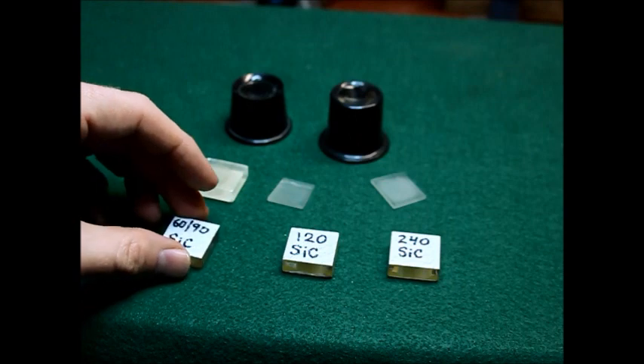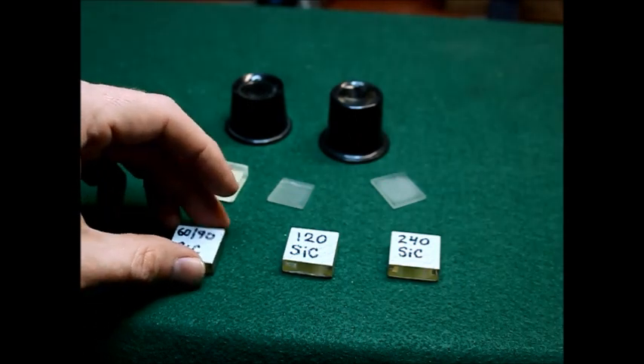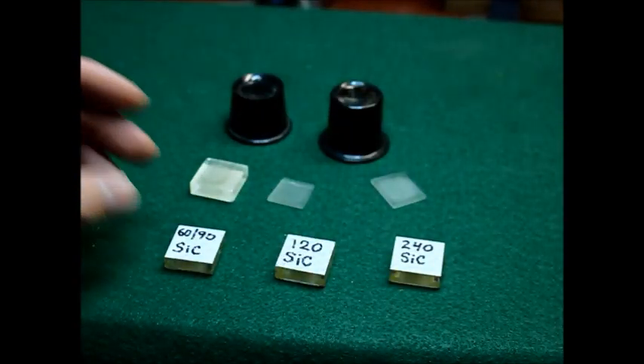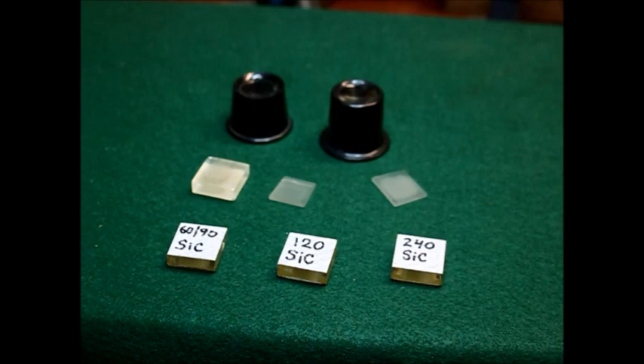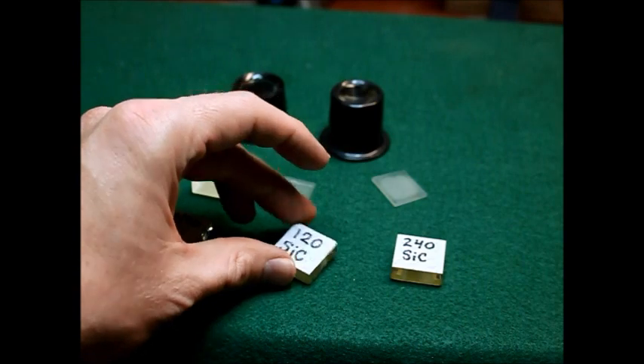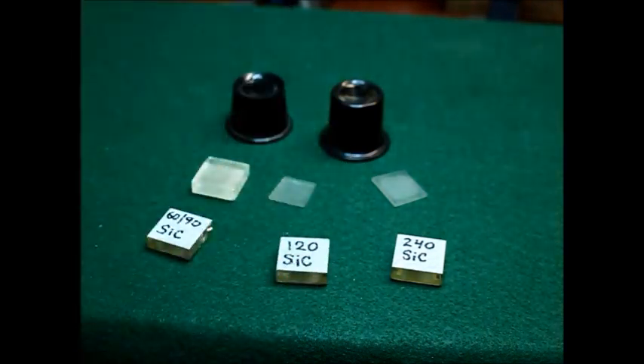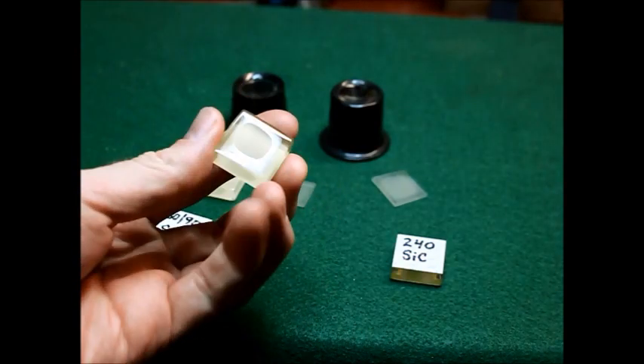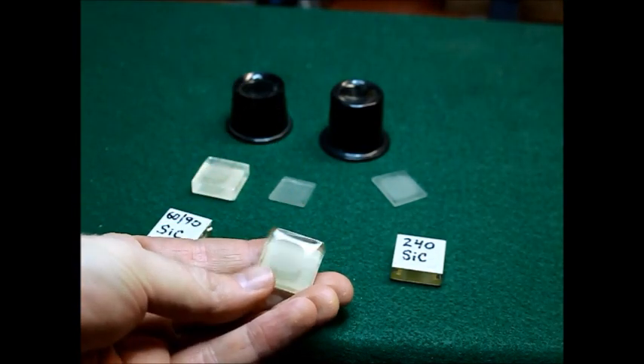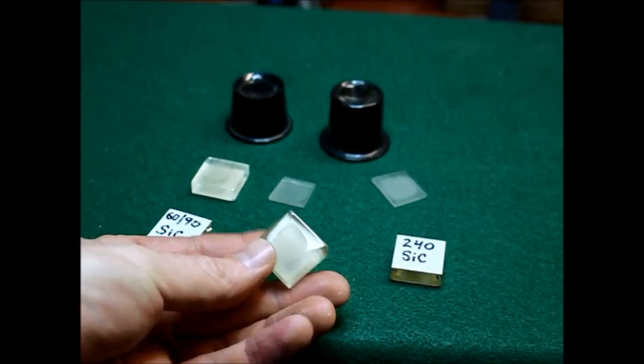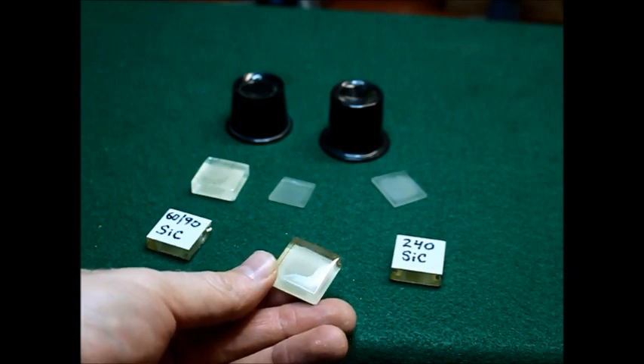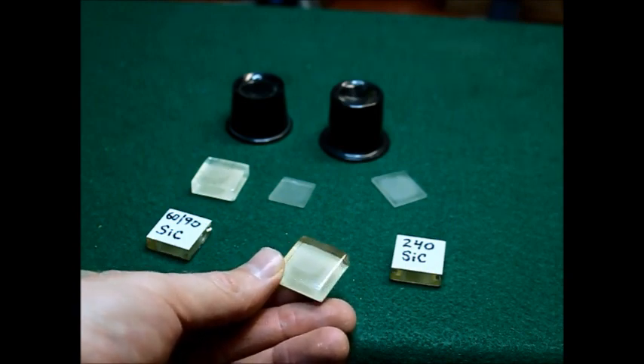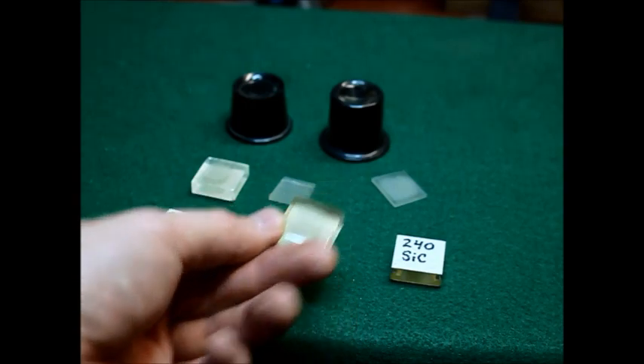I've also made some standards. And what I mean by standards are something I can compare the surface of the mirror to a known surface. So what I did was I got some of my silicon carbide or whatever grit I'm using and I've etched the tops of these little glass tiles. So now under a loop I can compare this surface with the surface of my mirror to see what are pits, to see what are scratches, to compare the two against this known standard.